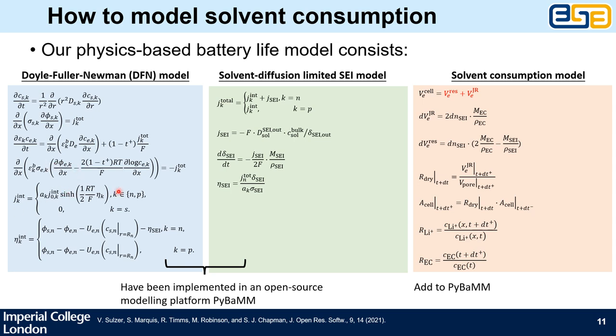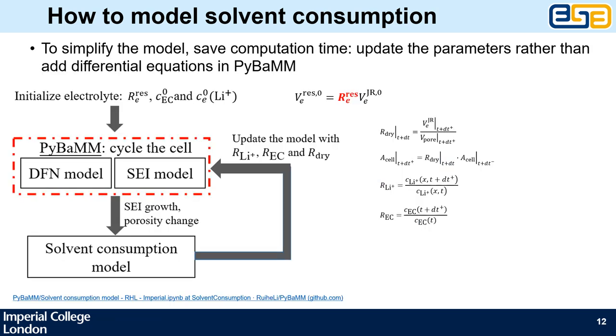These are the key equations of the model. The first part is the classical DFN model, which has been widely used in battery modeling. The second part is the mature SEI model. The first two models have been implemented in an open-source battery modeling platform called PyBaMM. The last part is my solvent consumption model proposed here, which mainly describes how electrolyte volume is being consumed and how that affects the dry-out ratio and the concentration of both lithium ions and EC. To make the model more efficient, based on the assumption that solvent consumption is a slow process compared to charge and discharge, we write our model outside the core of PyBaMM. Instead of solving differential equations, we implement this model by updating three parameters at certain cycles. This enables the model to be just one notebook, and I provide a link here which allows anyone interested to reproduce all my results.